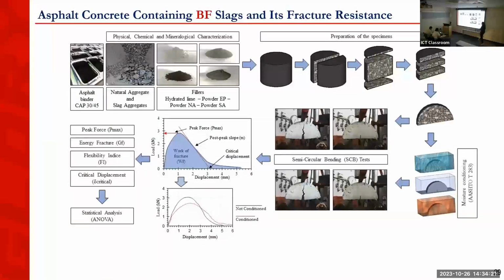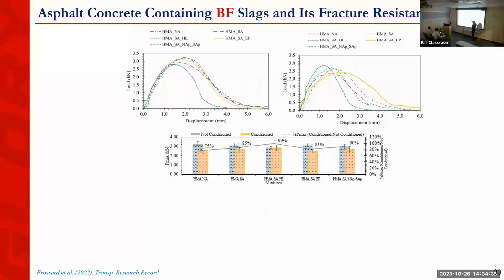This study also tried to evaluate how the same powders could affect the fracture resistance of the mixtures. So we did SCB tests before and after being conditioned. What we observed was that when we just evaluated the SCB test without moisture conditioning, all fillers kind of behaved the same. So we didn't see the effect of the chemistry of the fillers acting to improve the fracture resistance. But when we subjected the mixtures to moisture damage, then we started to have interactions of the chemical components of the filler with the aggregates and binder, and then the materials behaved totally differently.